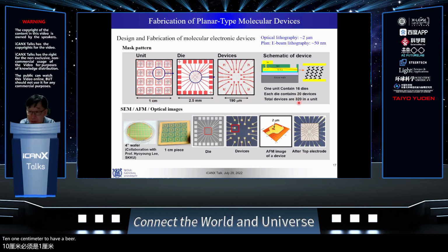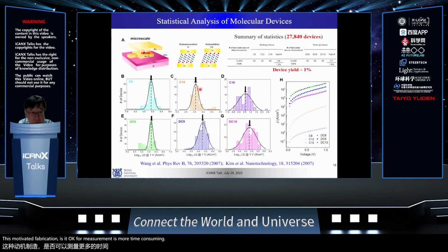Okay, so the problem is how you can measure many junctions. That's more difficult. Fabrication is okay, but measurement is more time consuming. So for example, students fabricate 30,000 junctions, and they measure individually. We didn't have automated probe stations, so if my student measures individually, you can imagine how many junctions you can measure per day. 100. If you measure 10,000 junctions, it takes 100 days.